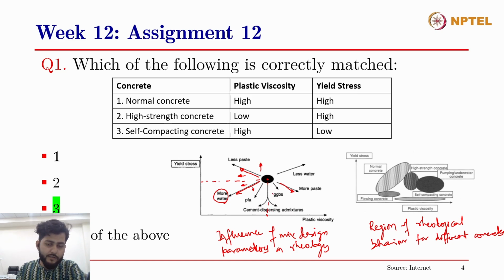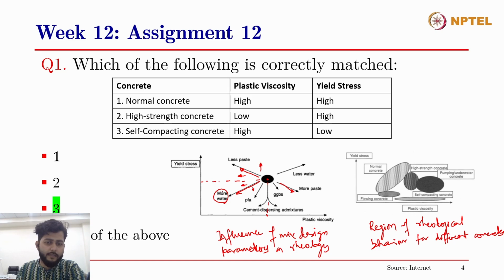In the case of cement dispersing admixtures, it could go both ways. The yield stress will anyway decrease, but it could decrease the viscosity, or it could increase the viscosity, depending on the application that you want. When you add a normal superplasticizer, it decreases your yield stress and it decreases your viscosity as well, right? It is a water reducer, so it will work more like increasing the water content. But when you add something like a viscosity modifying agent, VMA, it will essentially increase the viscosity due to its polymer structure. So even though the initial yield stress is lowered, the viscosity is increased. So cement dispersing admixtures can have both types of effects on viscosity, and therefore you need to use the different kinds of admixtures suitable for your application and need.